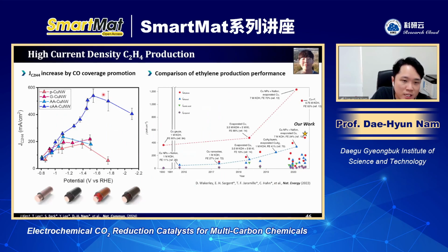In this way, we could enhance the partial current density of the ethylene compared to the other one; it was over 500 milliampere. And this result is located at this one.